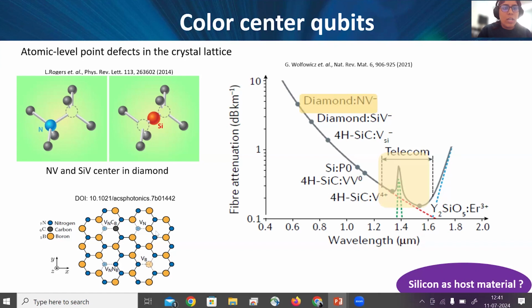So just for an example, if you take a diamond material, you can have a bunch of color centers in it. For example, the NV center is among the most popular ones, where you replace two carbon atoms with nitrogen in one place and keep a vacancy in the other place. So this is the nitrogen vacancy, so NV center. And this kind of point defect also has a spin to it due to the free electron it has in its structure. And then you can use this NV center for quantum applications because it fulfills the three requisites. It's quantum mechanical in nature. You can perform the principle of superposition and do entanglement with it.